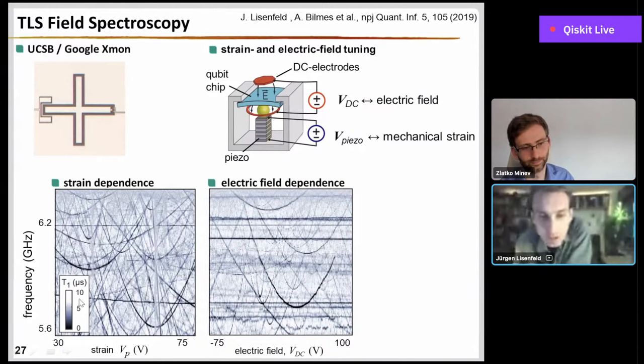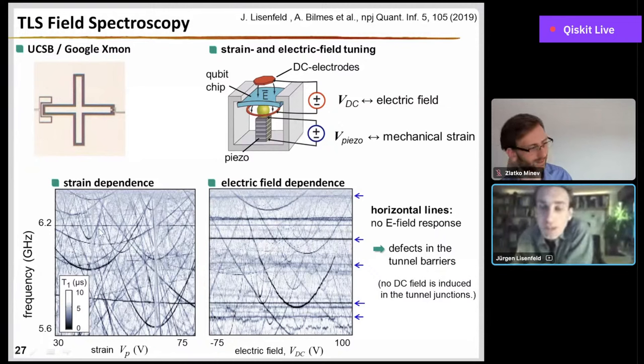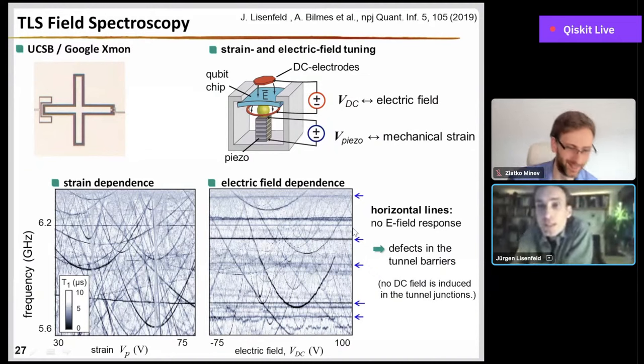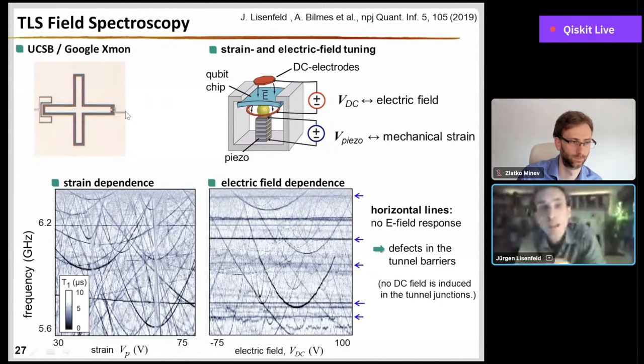Again, we measure the T1 time of our qubit as a function of the applied electric field or the applied voltage on these electrodes. And again, we can see some hyperbolas which reveal the defects on the electrodes, because these are exposed to the electric field and they respond as expected to the field tuning. However, you also see much more horizontal lines now compared to the strain data. It turns out that the only place where these electrodes do not generate any electric field is the tunnel barriers inside the Josephson junctions. Because we have a transmon, and you will not be able to put any DC voltage across the Josephson junction. It will just be compensated by Cooper pair tunneling. That's why in the junctions you never have any induced DC electric field, and that's why you can now identify all horizontal lines as defects being in the junctions. And this is a very nice thing.